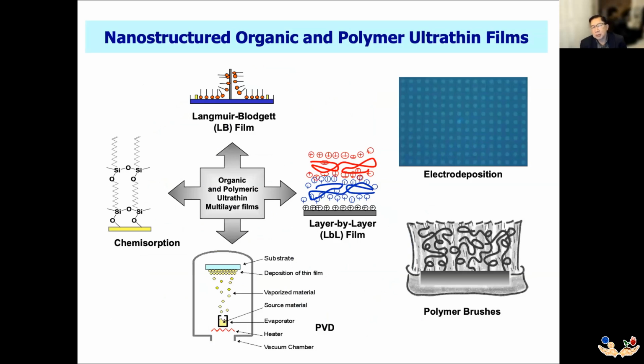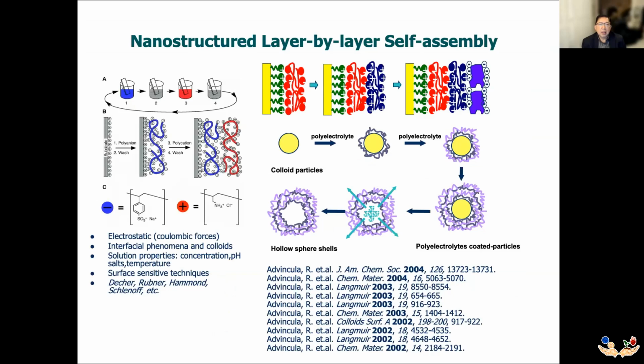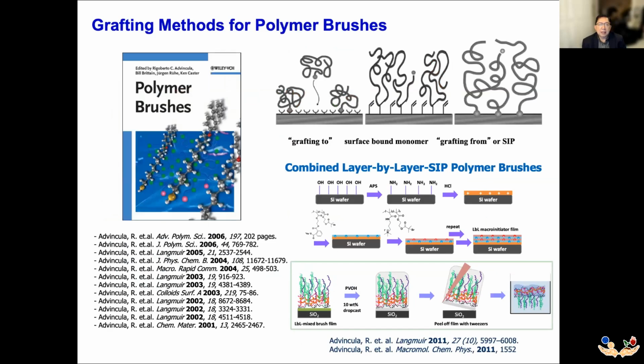A lot of this actually involves nanostructuring or surface structuring of these macromolecules or even in combination with different types of physisorption and chemisorption, where we control the layer by layer deposition, the grafting of polymers on surfaces, or their electrodeposition. Another interesting phenomena is based on layering of materials based on electrostatic interaction, such as in the case of polyelectrolytes or polyzwitterions that can be built up as layers or in the use of core shell, hollow shell particles. Another technique that is very important is the grafting of polymers on surfaces.